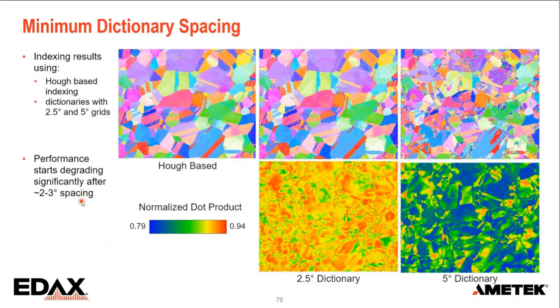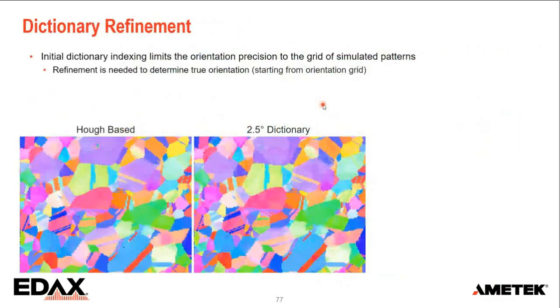So if you're interested in a texture or a grain size, that is probably a good value to use for dictionary indexing. 2.5 degrees will allow you to get good indexing results with a little bit of orientation jumps, but that's within the 2 degrees, let's say. You can get all the grain size and texture information that you need if you want to do the dictionary indexing. If you want to go smaller than that, we can refine.